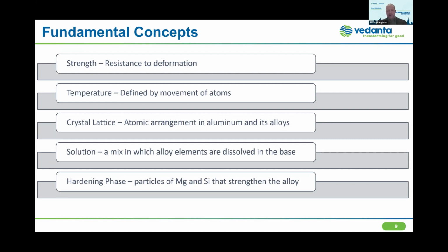Solution. This is an important concept. Basically, like you have hot tea and you put sugar in it, you are dissolving the sugar. In a similar manner, when we change the times and temperatures, we are solutionizing our metal, so that for 6000 alloys, magnesium and silicon, the primary alloying elements, we're dissolving those in the base aluminum, and we have a solution that, at least from a high level, is indistinguishable from the base.